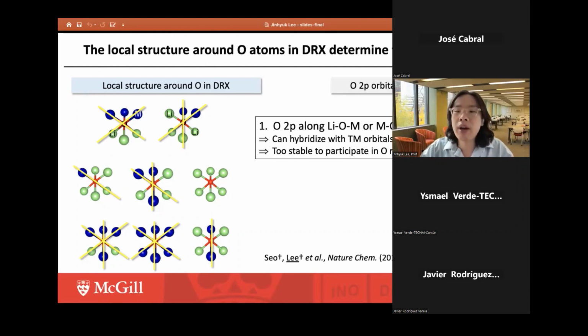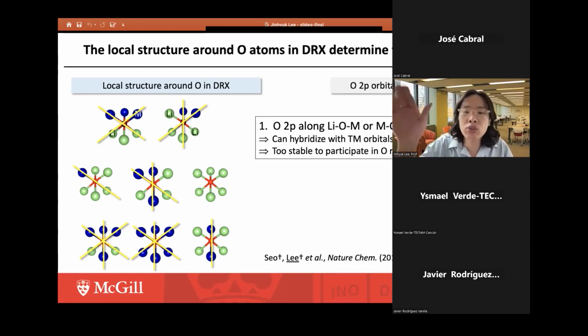And at the same time, we're also going to have a low energy hybridized bonding state. What happened is that these oxygen 2p orbitals become very low energy, stable oxygen 2p orbitals after the hybridization. And because, after this hybridization, the oxygen 2p energy of this particular orbital is too low, they will not be able to get extracted upon charging, right?